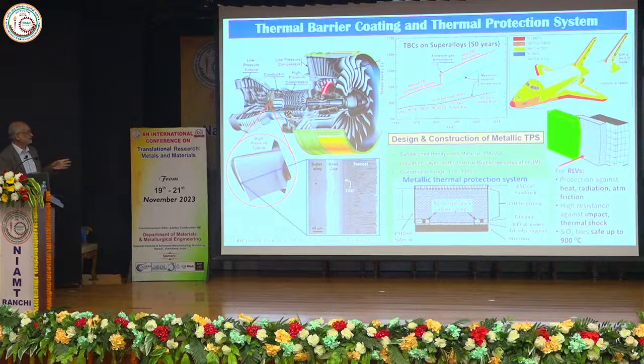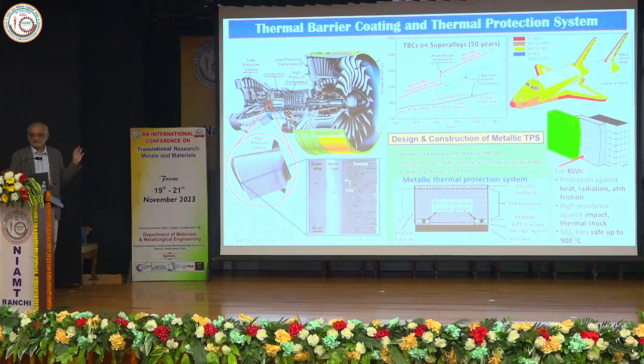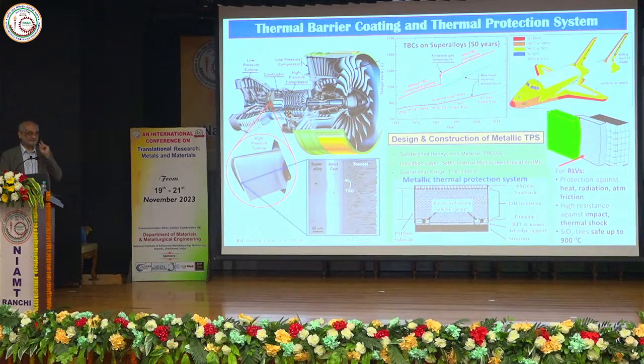This is the kind of thing every engineer would like to do someday, so that one can claim to have developed a turbine blade or a disc or a coating. One of the finest examples of engineering, because these blades are actually an 8 to 10 component system, single phase, and more than that, single crystal. Those who study metallurgy would know what a monstrous job it is to retain all of them in a single solid solution and develop only a single crystal, one single orientation.